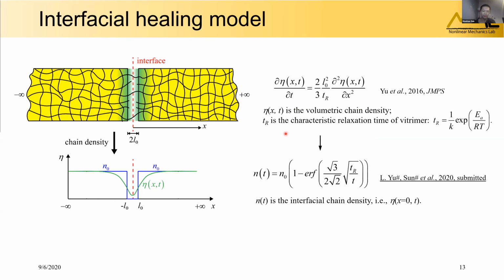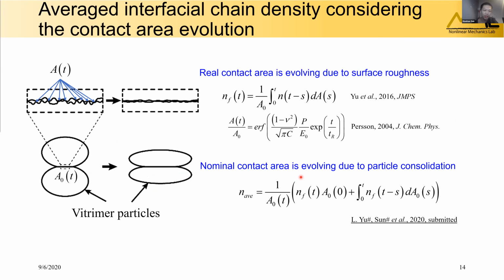The pressure does not appear here, but in practice, the pressure may also affect the healing if the surface roughness is considered. Note that the derivation of this formula has assumed molecular scale contact between the two surfaces. While surface roughness can prevent the uniform contact between the two surfaces and results in a smaller real contact area A than the nominal contact area A0.